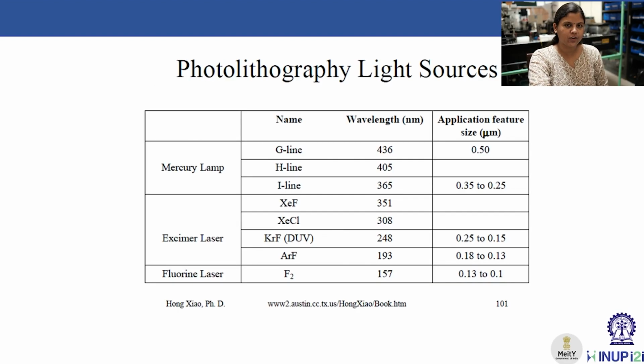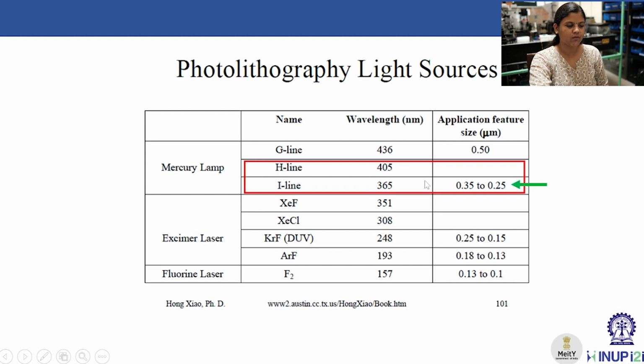Now there are various photolithography sources which are being used like mercury lamp and fluorine laser. In our lab we use the mercury lamp, which can give three wavelengths: 436, 405 and 365 nanometers. In our lab 405 and 365 nanometer are available, and we will be showing you by using the wavelength of 365 nanometer. If you look at the last column, we see that as the wavelength of the source decreases, the feature size that could be attained also decreases. That means with lower wavelength, higher resolution could be attained. But as we go in the deep UV region, the optics becomes costly, and hence in order to compensate that, we try to use wavelengths like 405 and 365.